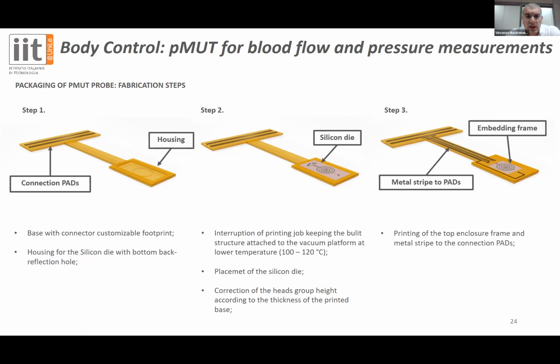Then the printing is interrupted and the silicon die is placed inside the housing hole. In this case, we change a little bit the temperature. We cool down the temperature of the printing platform to 100-120 degrees, starting from 140 degrees, which is the standard sintering temperature of the silver ink, in order to safely place the silicon die inside the housing, but also to minimize the shrinking and the swelling of the polystyrene printing substrate, and avoid in this respect some misalignment.